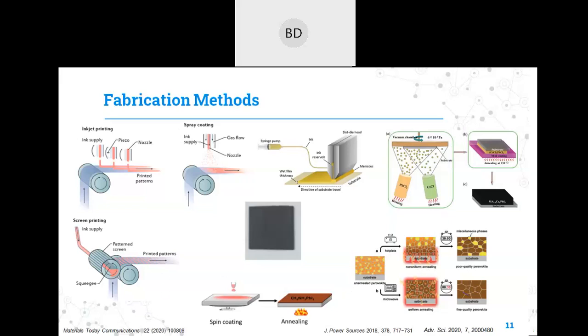So if you are going to study the perovskite on a laboratory basis, the most important technique used is the spin coating technique, because it's a very easy technique. You just need some precursor, drop it on the substrate and anneal it. Even the annealing has been made very easy nowadays. Earlier, people used the hot plate, but with the hot plate, people need to anneal it for around 30 to 40 minutes to get a good perovskite structure.